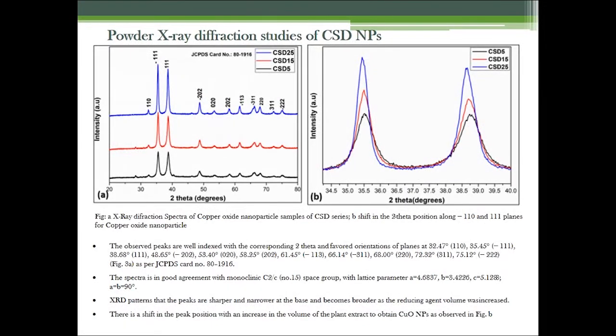Then coming to the powder X-ray diffraction studies, which determine the structural properties, crystalline phase determination will be done using this powder XRD analysis. Here we have observed various peaks which are well indexed with the corresponding 2 theta and favored orientations of the planes at 32, 35, 38 and 48, 53 and so on. This is with reference to the JCPDS card number 80-1916. The spectra is in good agreement with the monoclinic structure of the copper oxide nanoparticles. No additional diffraction peaks were observed, which indicates the high single phase crystal purity of the prepared nanoparticles.